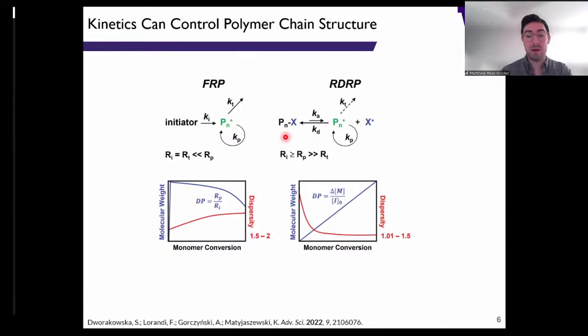So you have incremental growth pretty uniformly across all of my growing polymer chains. In order for this to occur, initiation has to be really, really fast relative to chain propagation. You can see here that you have a linear relationship between molecular weight and monomer conversion, and then this term called the dispersity ends up being fairly low at high monomer conversion.